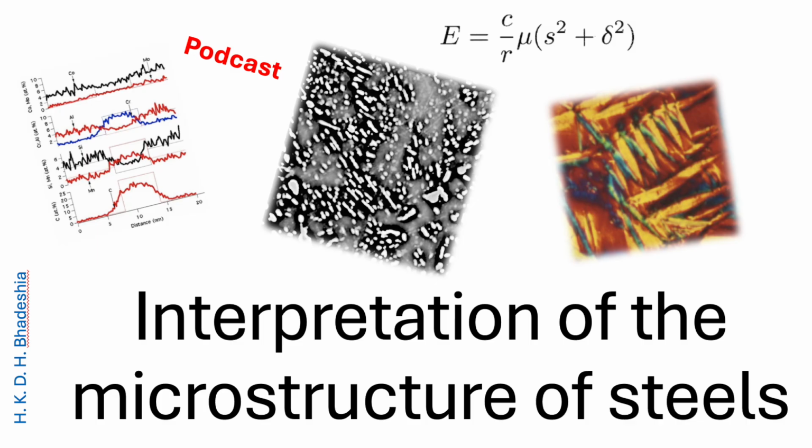Okay, let's focus on the reconstructive phases first, where that mobility and diffusion are mandatory. We'll start with ferrite. We know diffusion allows for these complex shapes, so what stands out about the different morphologies of ferrite? Well, the shape difference depends entirely on where the ferrite decides to nucleate. When ferrite forms at the austenite grain boundary, the gamma boundary, we call it allotriomorphic ferrite. Allotriomorphic. And because it's growing fast along that boundary, its shape is dictated by the boundary itself. It doesn't reflect its own internal crystal symmetry. So its shape is just a shadow of its surroundings. Precisely. Now, in contrast, you have idiomorphic ferrite.